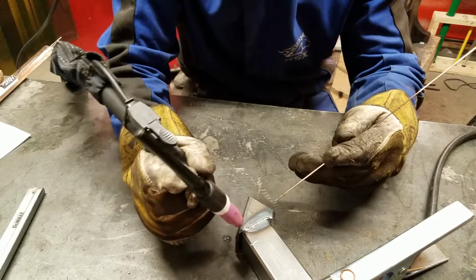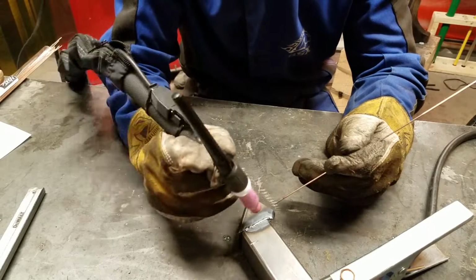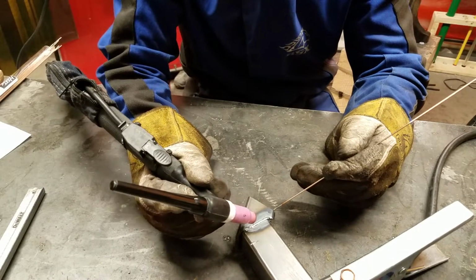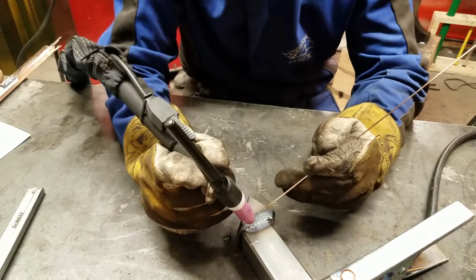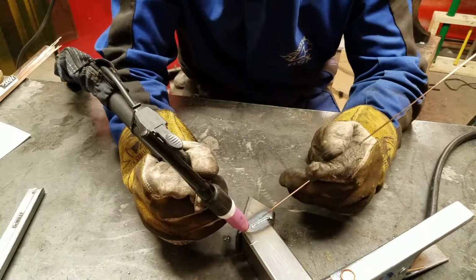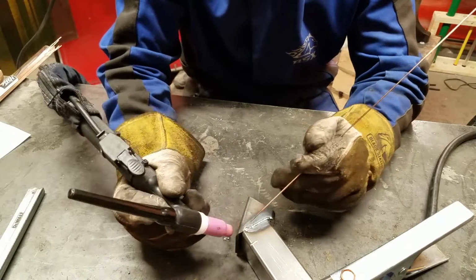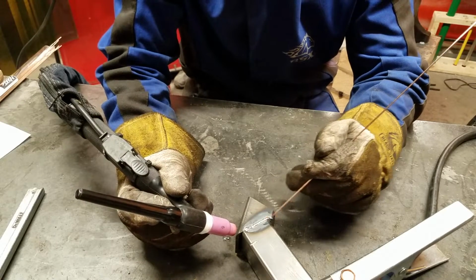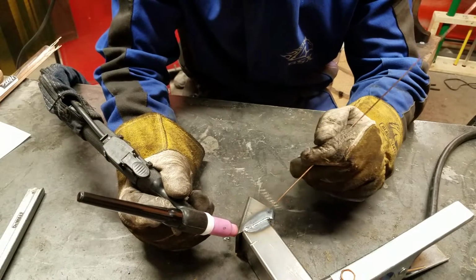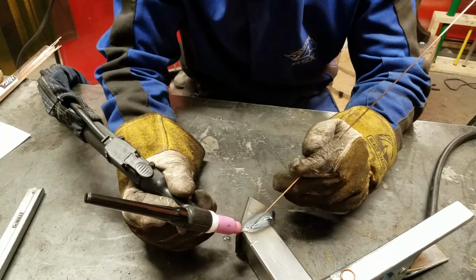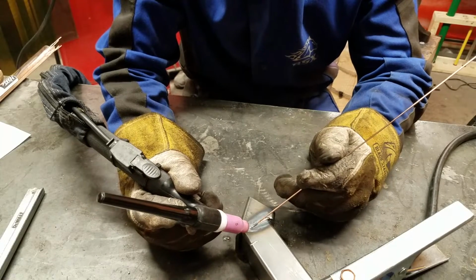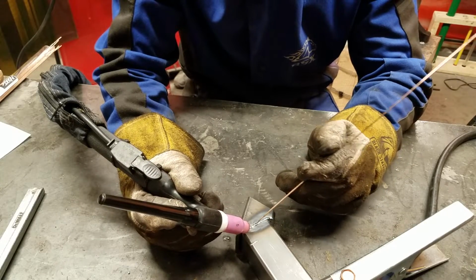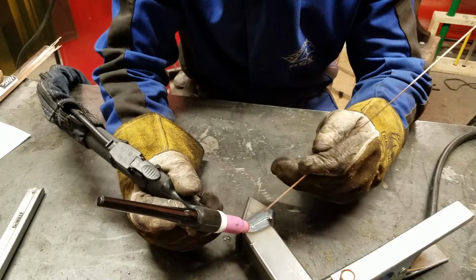But that's the idea. I also think that my angle was too far back. I was probably closer to 45 degrees instead of just 15. So we can go back over. You can see the coloration here. This is called the heat affected zone. So this area of discoloration is where the steel's molecular properties were changed. And so now it's a little more brittle there from having gotten so hot.